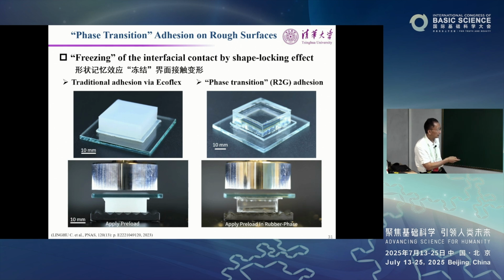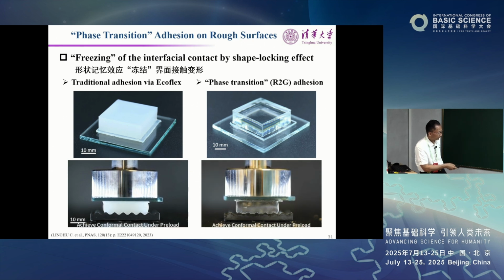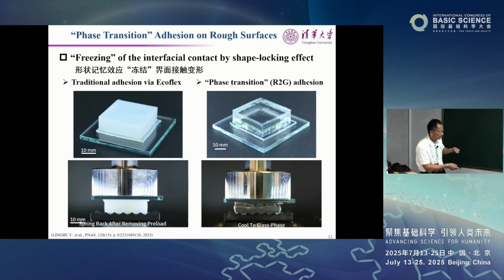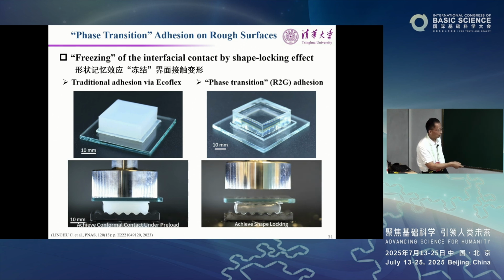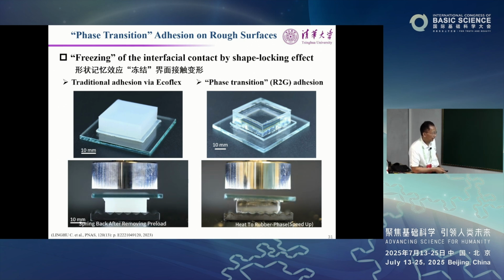Now let's turn on this phase transition adhesion. You push it down, you establish contact, but you don't let go at that moment. You cool it down, okay? You cool to glass phase. Remember, all the energy will be locked, temporarily frozen. In this case, you let go, see? You have well bonded this interface. Okay, how do you release it? You just simply heat it up. You heat to the rubber phase, the energies wake up, right? It becomes spontaneously detached. This is the idea of phase transition adhesion.